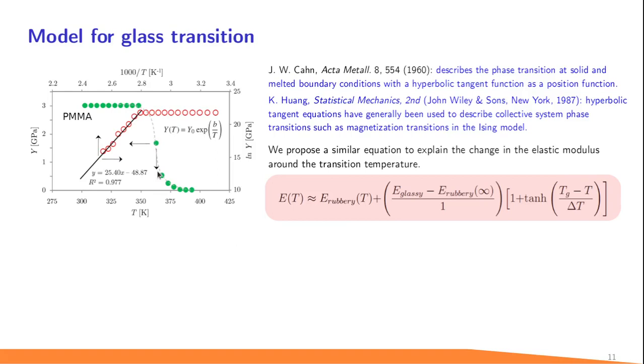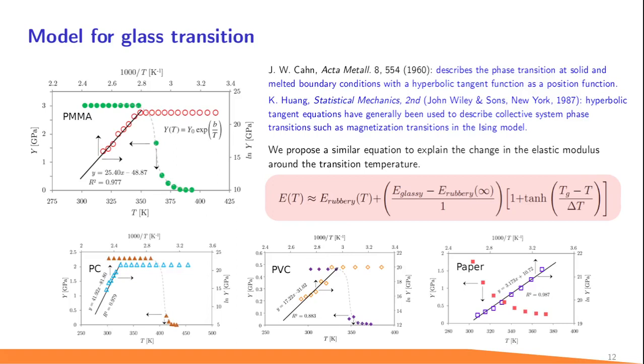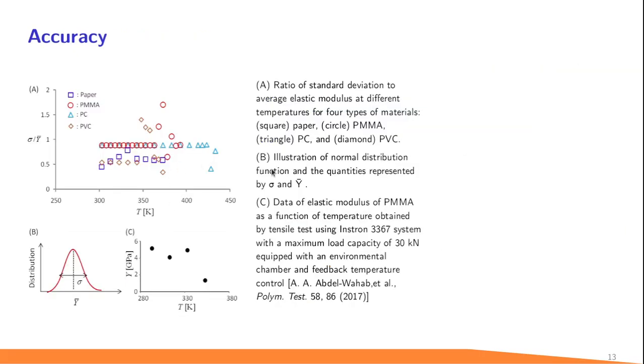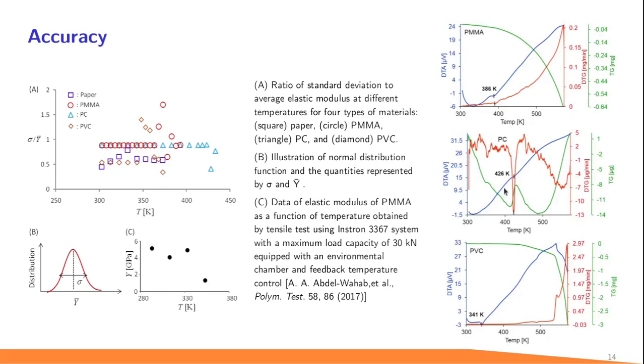And to justify our estimation results, we also directly measured the glass transition temperatures of the polymer samples and obtained a consistency between the calculated results and our experimental observation. And we also checked the accuracy of the estimation and we are very confident that the accuracy is acceptable.